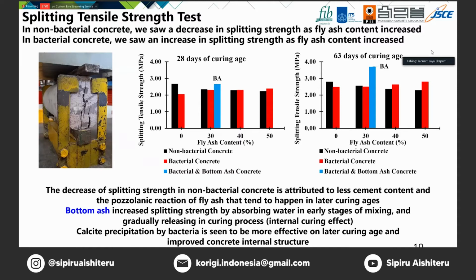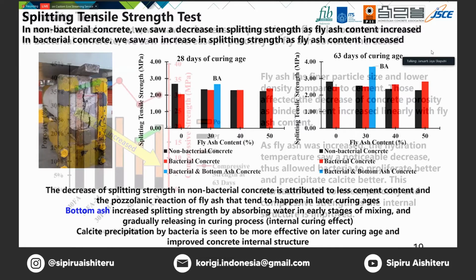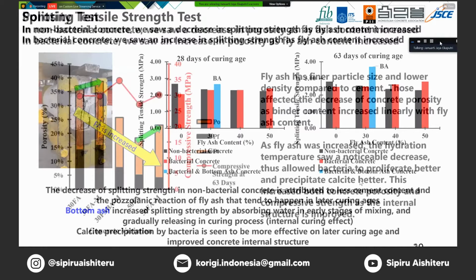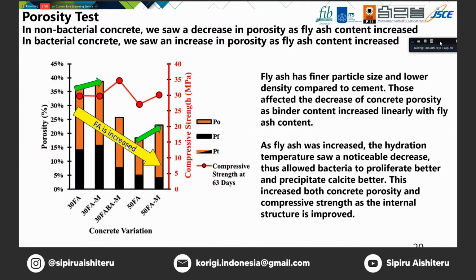And if we analyze the microstructure of concrete, we found that at the later age, as the ash content increases, the pore becomes denser, so it reduces the pores of the concrete. And especially if we have bottom ash incorporated with the microbes, we'll see the product of bacteria and the role of the sodium hydroxide in the next slide.